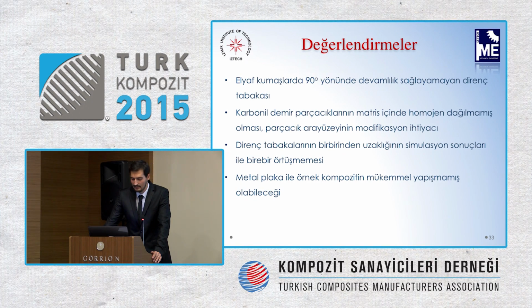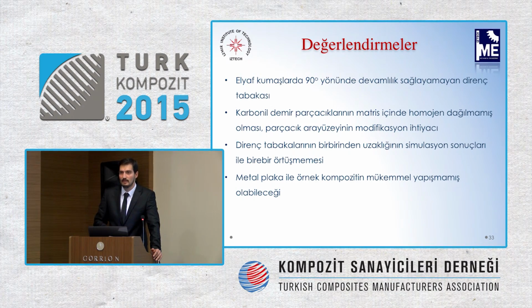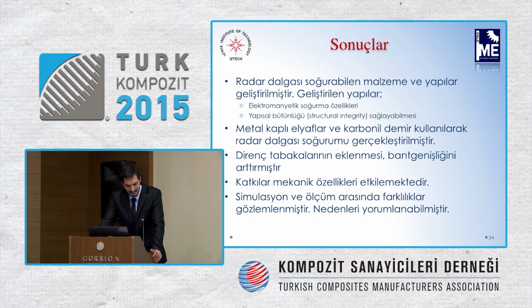The microstructure is not distributed in a homogeneous fashion because the materials have different densities. Therefore, different particle sizes might be required, or a different modification might be used. The distance between the resistive layers has to be similar. They have to be equal. And lastly, the metal plate on the last part should be perfectly adhered. Sometimes there might be gaps, and this will have an impact on the result.